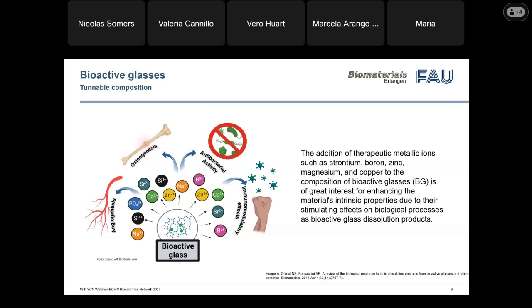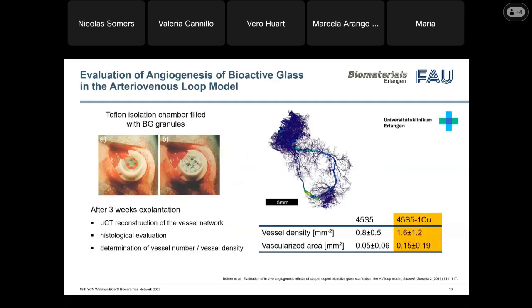But there are also elements which could have dual or multiple effects. For example, zinc can stimulate bone formation while also having an antibacterial effect. So with this approach, the functionality of bioactive glasses has been quite expanded. And one example I show in this slide.